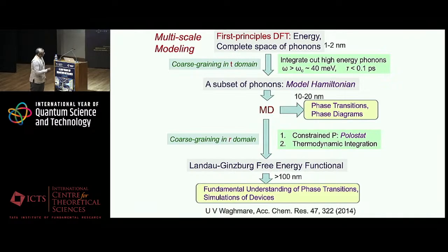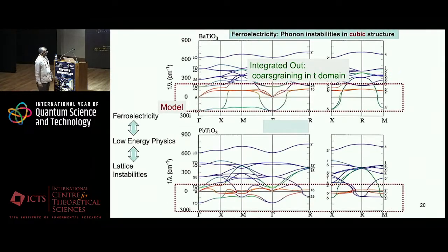Then we do coarse-graining in the real space domain, and there we develop some of the tools on our own. Like a thermostat, we have a polostat, and that allows us to get a Ginzburg-Landau type theory, essentially from first principles. And once you have this theory, you can access much longer length scales, hundreds of nanometers, and that allows not only fundamental understanding of these phase transitions, but also simulations of devices. So this is what comes out of this first principles calculation.